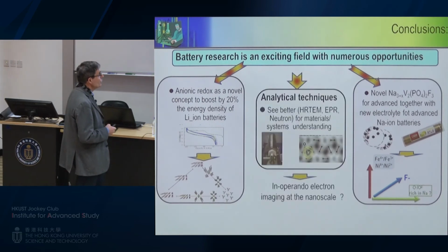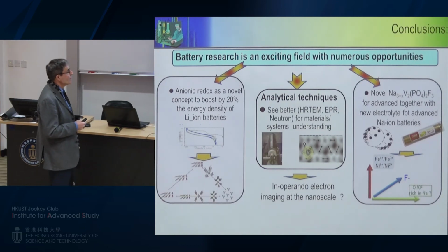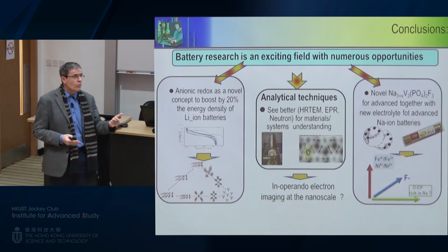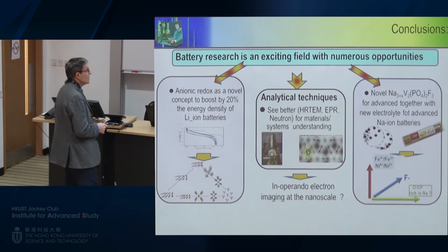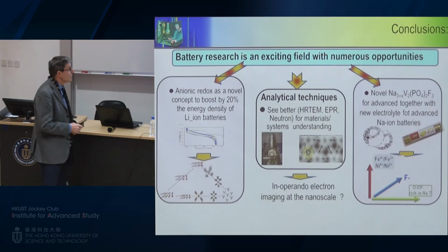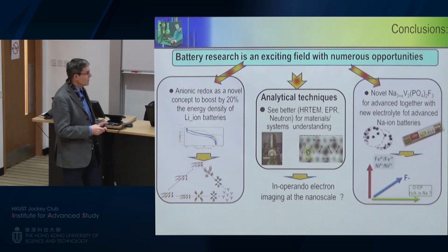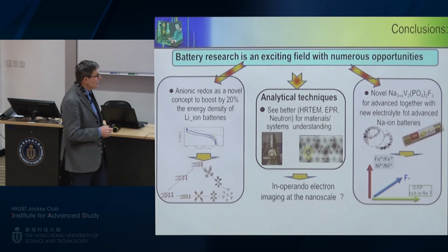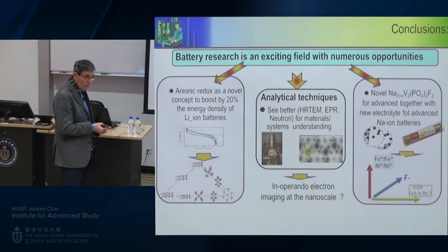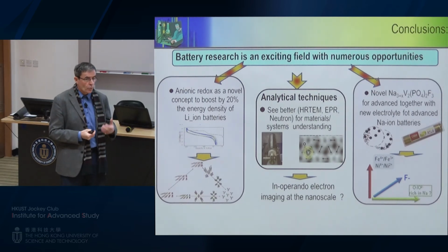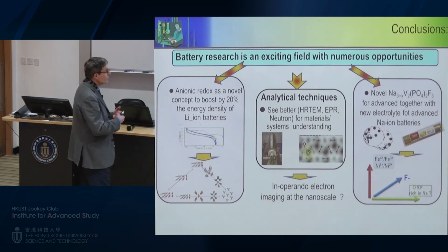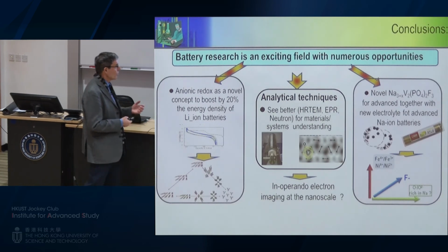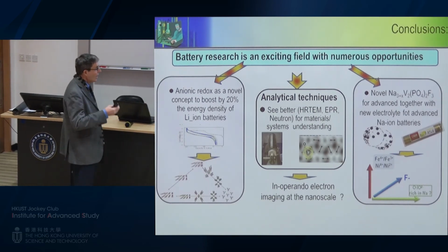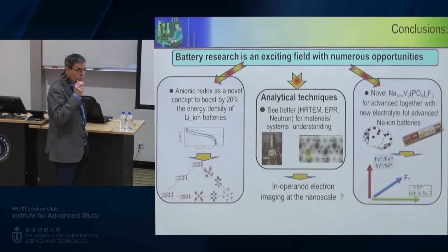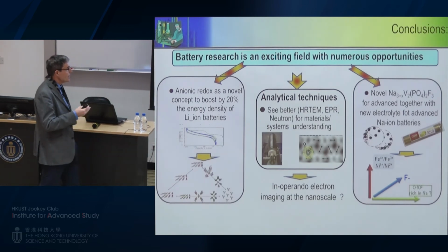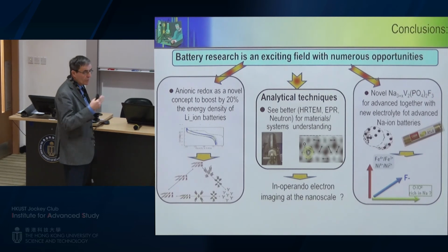Also, through this presentation, I showed you how important analytical techniques are. Because we were able to see this kind of dimer by high resolution electron microscopy, we were able to come out with the mechanism that we propose. And of course, what will be nice in the future, for people trying to push the frontier of the analytical techniques, is if we could really have an operando technique which enables us to look at the electrons during the reaction. Because, as you know, all the energy-related concepts, dealing with either electrochromics, photovoltaics, or water splitting, are always based on redox reactions. So I think if we could really spot the electrons, this could be a revolution in electrochemistry, the same revolution that we had in materials science when microscopy came out.